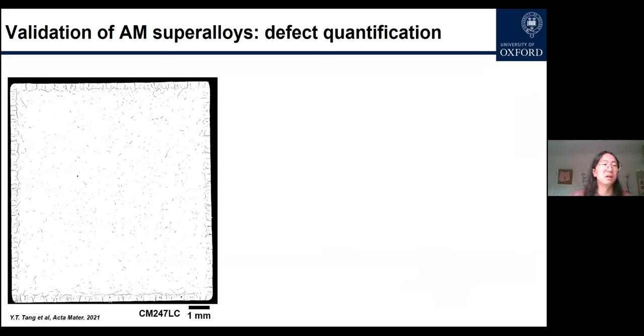This is a binarized image of a CM247 LC material. You can see how many cracks there are in here, and they're just not good. You won't be able to trust your plane if it is made by this material in this method. But just to be frank, this material itself, if it is used by some other method, can be completely flawless. So don't worry when you get on the jet plane. But we know this method is not very good for CM247, which is a gold standard.